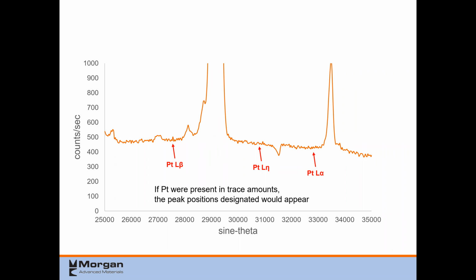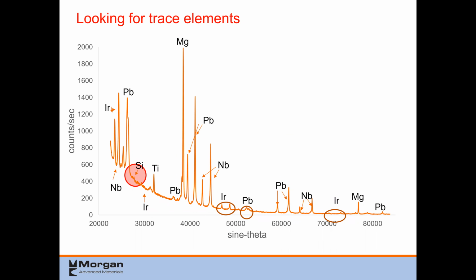So they wanted to know what it was, if I could tell them that. And I said, yes, I absolutely can. And so I did a full spectrum in order to figure out what the contaminant was. And all of the peaks that you see there are expected, except for that tiny little silicon peak. And that tiny little silicon peak is about 0.05 weight percent. It's very tiny, but it was enough to show that that's where the contamination was coming from. And I told them that it was silicon, and they were overjoyed because they knew exactly where in the process that was being introduced and were able to fix their process.